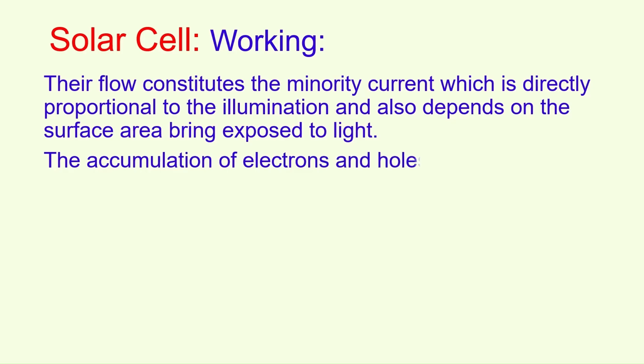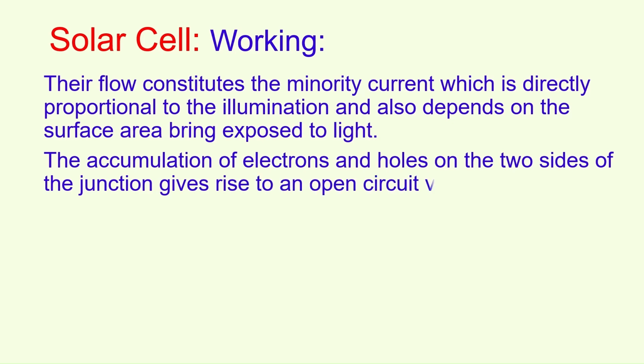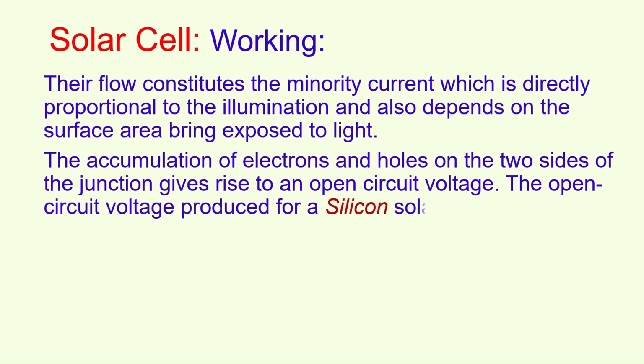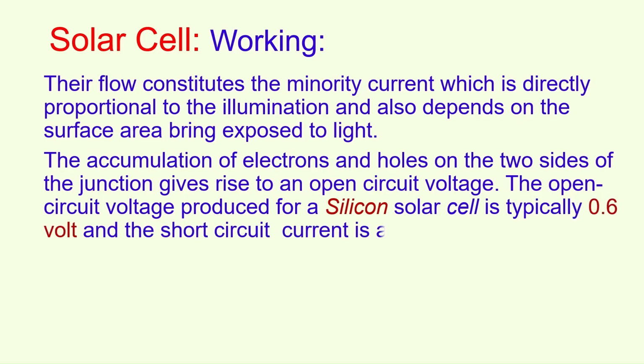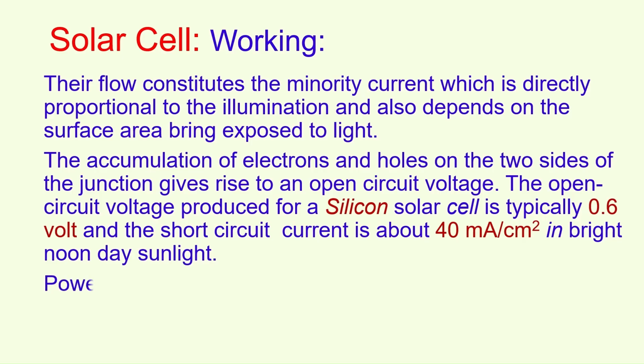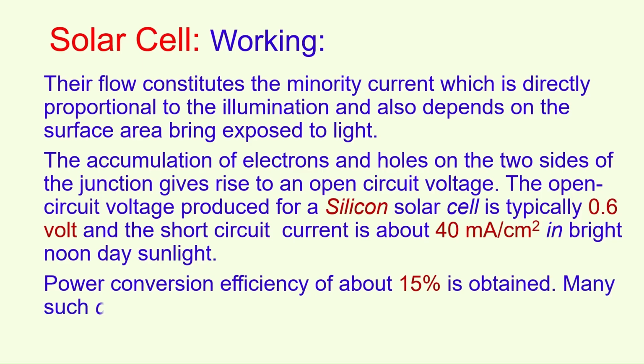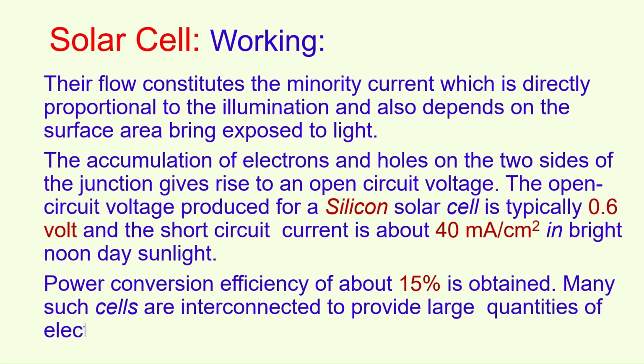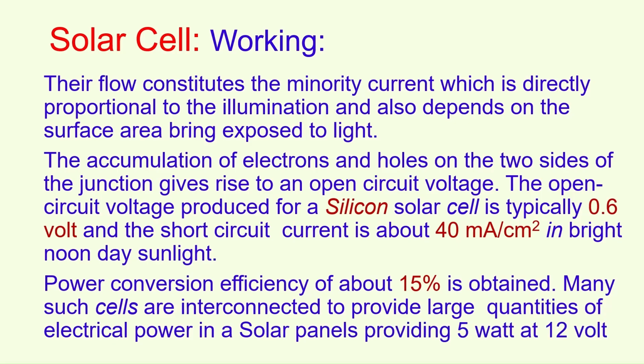The accumulation of electrons and holes on the two sides of the junction gives rise to an open circuit voltage. The open circuit voltage produced for a silicon solar cell is typically 0.6 volt, and the short circuit current is about 40 milliamperes per centimeter squared in bright noonday sunlight. Power conversion efficiency of about 15% is obtained. Many such cells are interconnected to provide large quantities of electrical power, in a solar panel providing 5 watt at 12 volts.